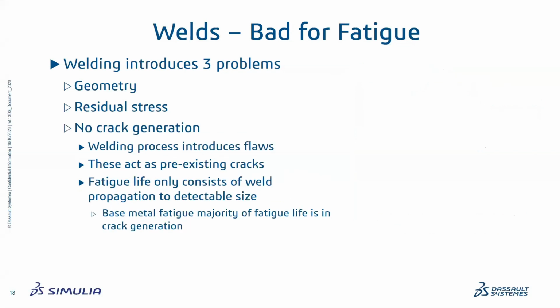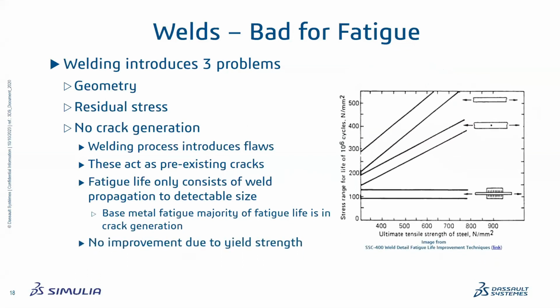And then the final reason is that just by welding something up, you actually introduce a small crack. And the majority of life in base metal fatigue is actually creating the crack. Once you've got the crack, growing the crack tends to be fairly short. But welds are bad because they always have a crack, at least conceptually. So that life of generating the crack is not there.